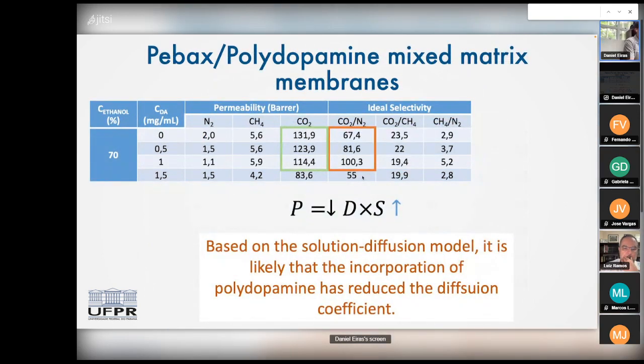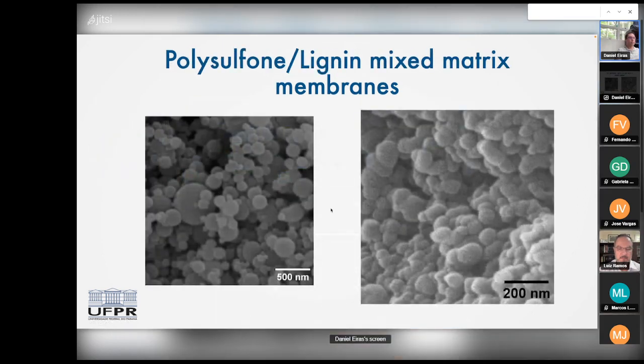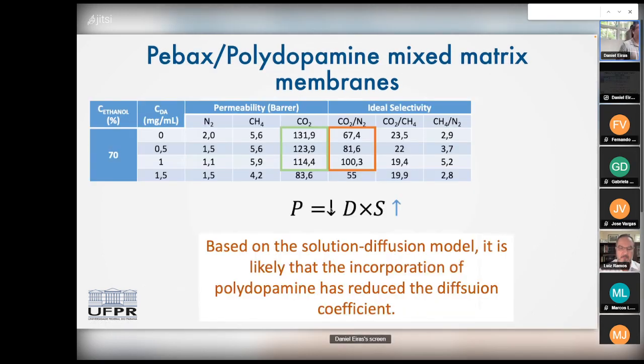So if you increase the selectivity, but we decrease the permeability, what happened is that the diffusion coefficient was reduced. We are mostly sure that this term S is increased with the incorporation of polydopamine. We have information from the literature that the term S has increased. So in order for the permeability to be reduced, the term D has to be decreased.